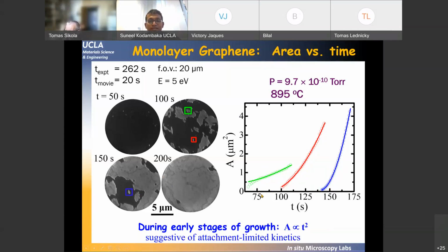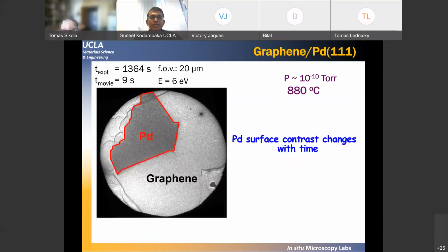This is interesting because initially we weren't sure why this would happen. Nevertheless, all these islands grow as a function of the square of the time, based on which we know that the limiting step during the growth of graphene is the attachment of the atoms to the existing island. So to understand this behavior, we again focused on the reflectivity data.